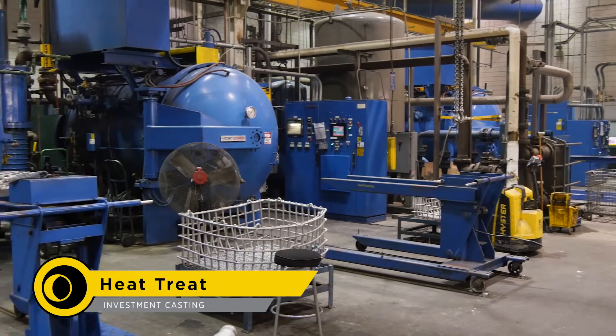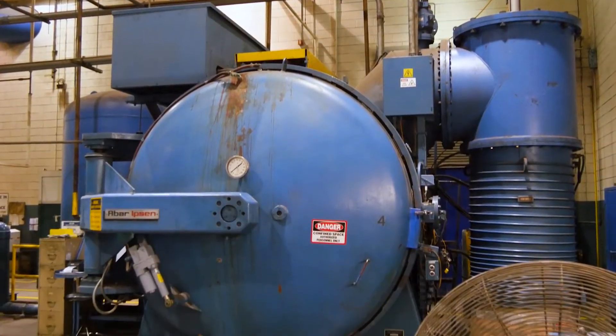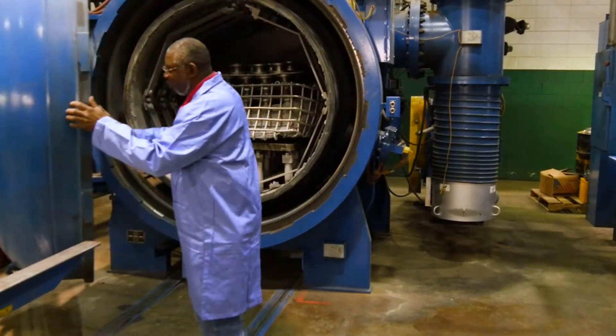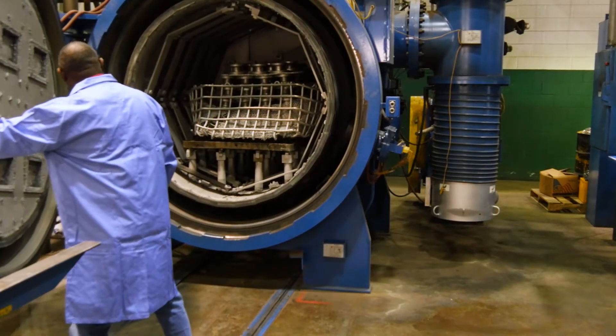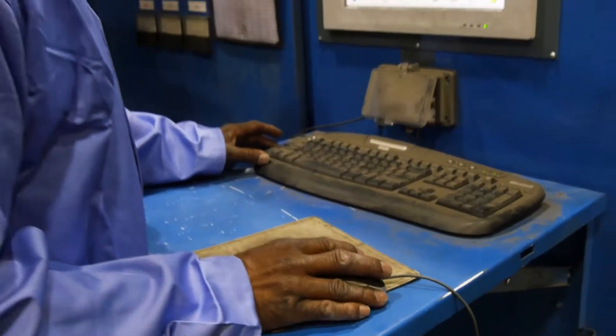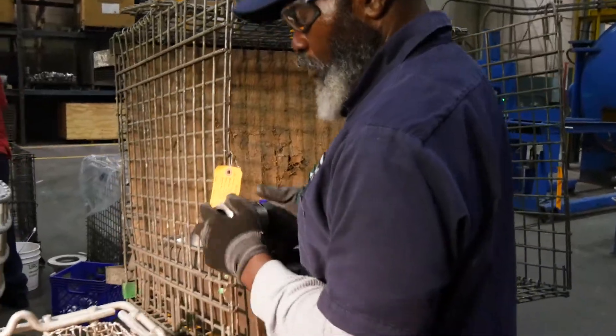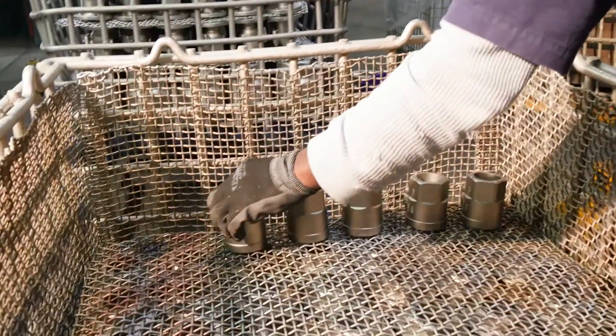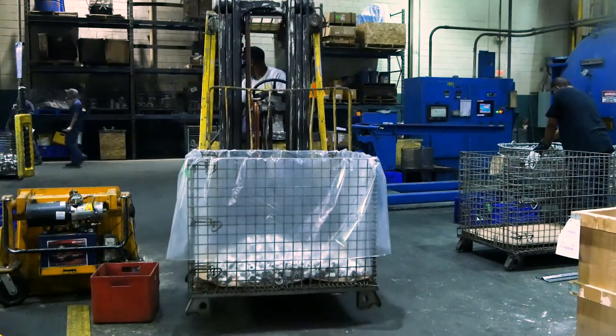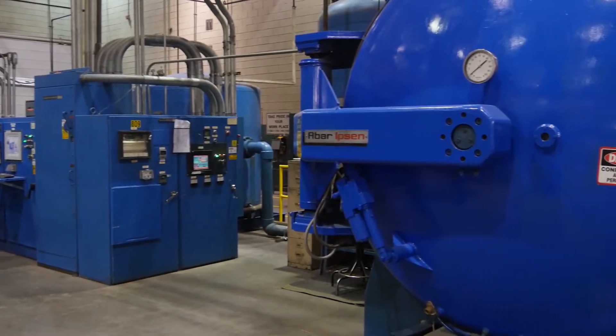The final step in the foundry is to subject the castings to heat treatment. This is beyond what is required by ASTM standards. Apollo valves utilize specially designed vacuum furnaces to ensure pinpoint thermal accuracy and eliminate surface scaling during the entirety of the heat treatment cycle. This heat treatment procedure is critical in ensuring that the corrosion resistance and mechanical properties produced are consistent and highly repeatable. The castings are high-temperature solution annealed and quenched to lock in the desired microstructure that prevents segregation-induced corrosion sensitization.